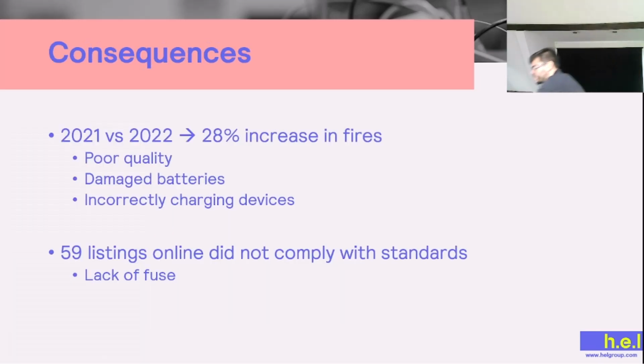So what are the consequences of misuse of lithium-ion batteries? Well, between 21 and 22, there was a 28% increase in fires reported linked to lithium-ion batteries. These fires were linked to poor quality batteries, damaged batteries, and incorrectly used charging devices. Also, Zurich Insurance did some research and found that at least 59 listings online did not comply with the standards. For example, one of the things they found is that the batteries lacked a fuse, and fuses act as a barrier that prevents further damage.